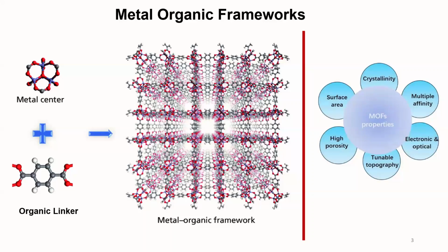Basically, they are crystalline porous materials constructed from the coordination of a metal center with an organic linker, and you get very beautiful and highly ordered crystalline materials which have metal centers connected by organic ligands. One can play around with the organic linker, so you can introduce a number of functionalities here. If you put acid groups, that is going to behave as acids. If you introduce basic sites like NH2, that is going to behave as basic sites. Basically, one can easily tune the properties of MOFs by designing an appropriate ligand.